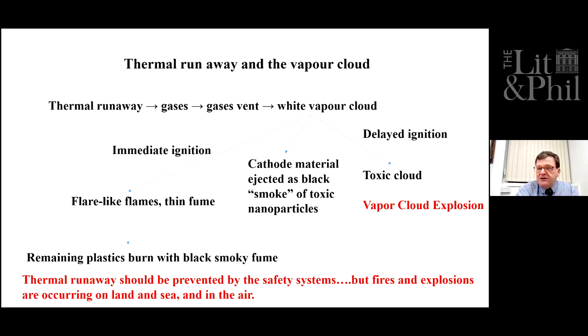If, however, it doesn't ignite immediately and you get delayed ignition, which has happened, then you can get a vapor cloud explosion. A vapor cloud explosion can give rise to overpressures of the order of 6, 7, or 8 atmospheres, and a tenth of an atmosphere is sufficient to kill you. Now, as I've said, the thermal runaway should be prevented by safety systems, but most of these are designed to stop the electrochemical processes. And so by the time they are deployed, it's simply too late. And fires and explosions have happened on land, in the air, on the sea, and indeed under the sea.